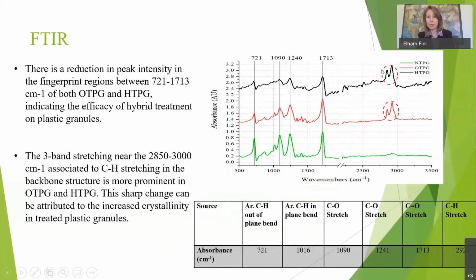On the other hand, in this region, we can see an increase and a sharp peak appearing, which may indicate the crystalline nature of the treated plastic. So the green is not treated, and as soon as we treat it, we get these structures forming. A sharp peak in this range is an indication of the crystalline structure. So we know that with this treatment, we make the granules even more crystalline. And it helps us with the structure of the whole composite when we have more crystalline plastic. But that was not the main focus. As I mentioned, the surface treatment and making it compatible was the first goal, but we got this added advantage of more crystalline structure.